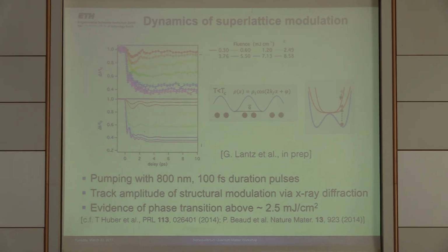The reason I'm putting this up is just to show that it's possible for us to drive the pre-martensitic to austenite phase transition. We can suppress the superlattice. The way we see that is a character change in the dynamics as we cross a particular threshold boundary. So this is actually a calculation. This is the actual data.